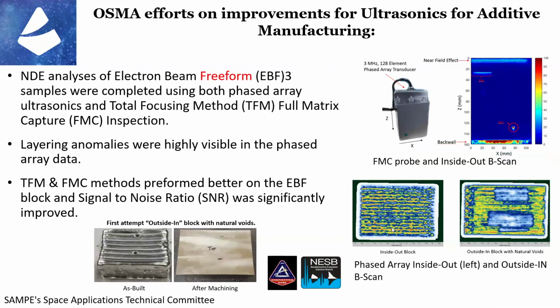It's very interesting kind of what happens, especially with the layering. So this was a block that we made on our freeform, which was the previous video that I showed. It's an electron beam freeform machine that we have here at Langley. And you can see the block as built down here at the bottom. Certainly, you can see all of the different layers that were in there. But we intentionally put these defects in there and then machined it so that we could actually do the phased array and full matrix capture systems on it.